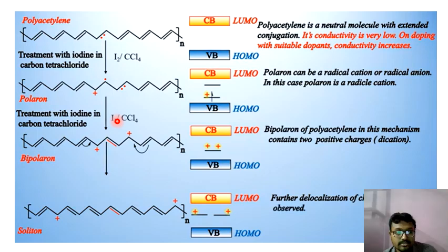So we will get this cation positive charge on this polymer chain, right? So, cation radical. Okay. Now there are many more Lewis acid molecules, so the second electron is moved. This second electron is moved, and we will get again an extra positive charge here. Now this radical and this radical combine, forming this double bond. Now what is happening? A dication is formed, right?